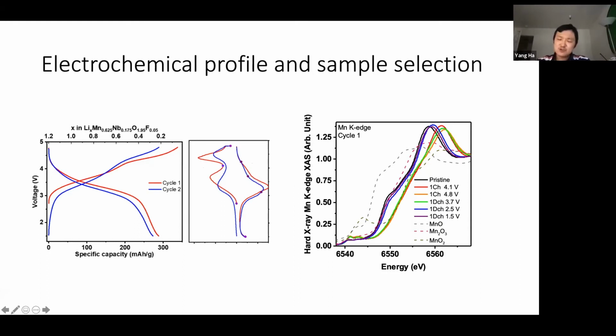Traditionally, people use hard X-ray, and here let's take the manganese K edge as an example. We have the reference for manganese 2+, manganese 3+, and manganese 4+. This is good enough for us to see we start with something in manganese 3+, we oxidize it a bit, and when we charge it to high voltage, it becomes manganese 4+, and then it goes back. But this is only qualitatively good, because we only know the starting point, the end point, and something in between. It's really hard to tell whether the valence is 3.2 or 3.5.